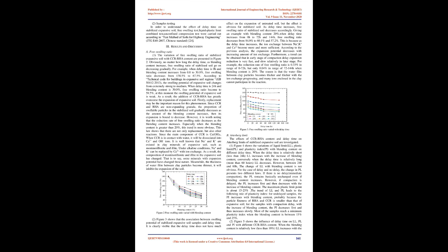3. CCR. The CCR was collected from an acetylene gas plant located in Huiya, China. Because the natural CCR is wet, it was dried for 24 hours at 105 degrees, then ground in a universal grinding machine. The particle size of ground CCR is shown in Figure 1 and its particles are very fine and uniform. The main chemical composition of CCR is CaO and its proportion is more than 70%. B. Testing methods. 1. Samples preparation. According to previous research by the author, the optimum mixing ratio of 35:65 CCR/RHA can obtain the best strength 14. Therefore, in this study, the ratio of CCR/RHA adopts 35:65.